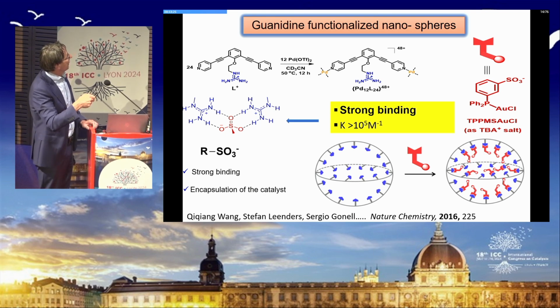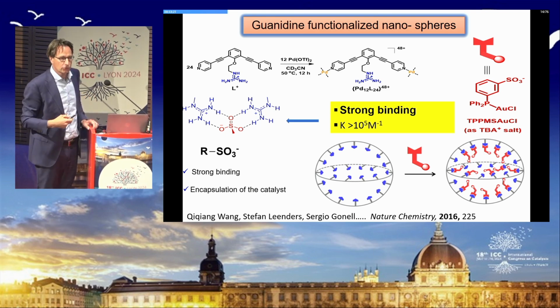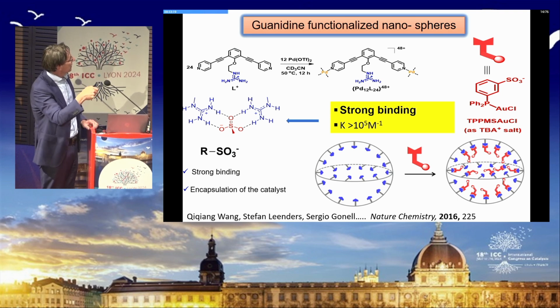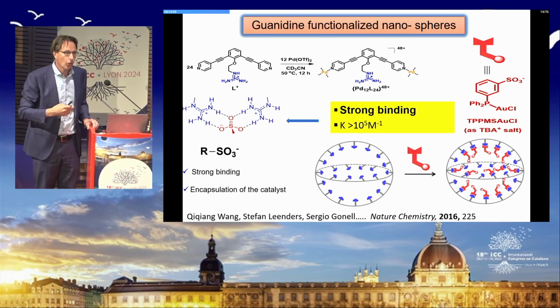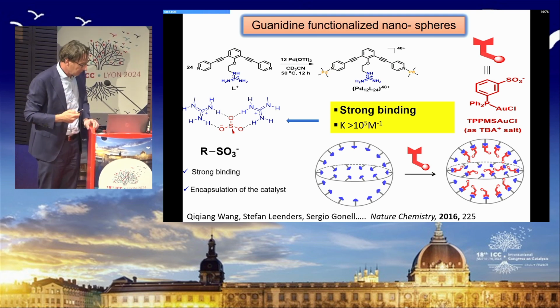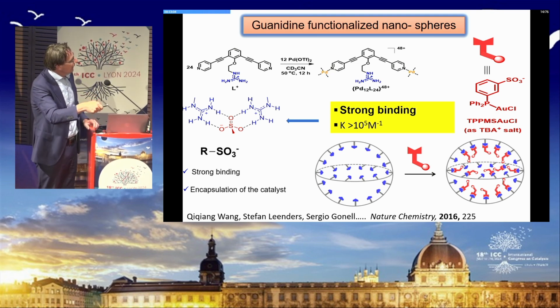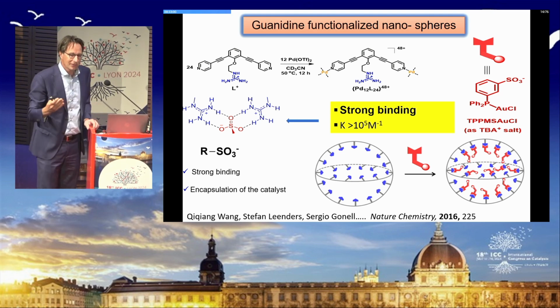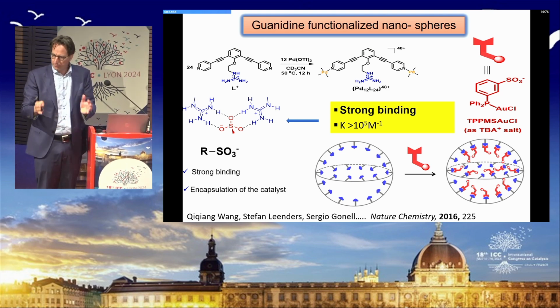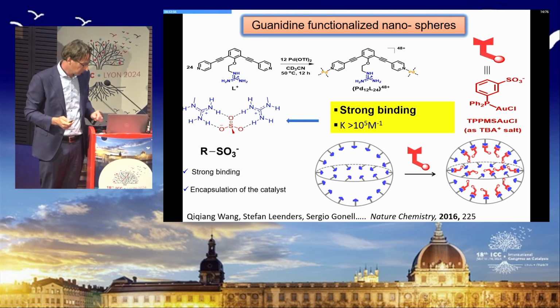at the inside of this molecular nanostructure. And these guanidinium binding motifs are known to strongly bind to sulfates because it's ditopic binding, and we established that binding of this sulfonated gold chloride complex is very strong, so association constants are over the 10 to the power 5. And we can upload as many gold complexes as we want, up to 24, which is the maximum, and then you have the proper stoichiometry between the two.